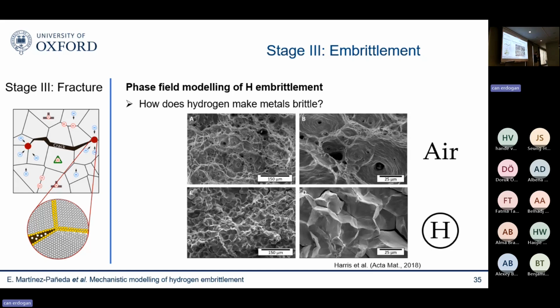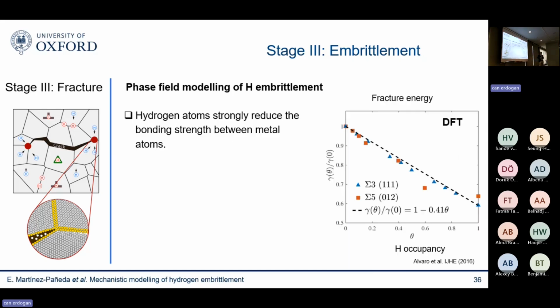In my opinion, in summary, there are three key ideas to understand this. The first one is that when you look at the problem at atomic scale, for example, we're running DFT calculations, you can see that the surface energy or the fracture energy of your metal is very significantly degraded with hydrogen. So this is surface energy versus hydrogen occupancy for nickel. These are DFT calculations for two types of grain boundaries in nickel. And you can see that if your grain boundary happens to be full of hydrogen, an occupancy of 1, then you're reducing your fracture energy by 40%. So now the next question becomes, okay, this seems like a possible scenario. If my grain boundary is full of hydrogen, it's going to be much weaker.